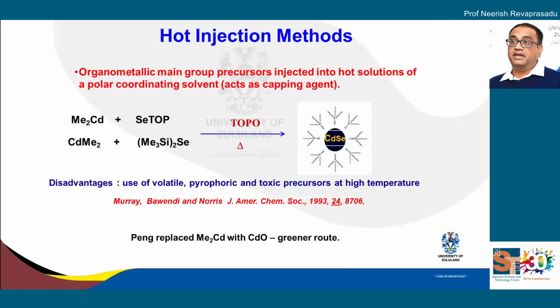Now, going back to the history, this was the first route to making cadmium selenide quantum dots, which won the Nobel Prize in 2023. They use dimethyl cadmium and trioctylphosphine selenide, or dimethyl cadmium with this bis(trimethylsilyl) selenium complex, and thermally decompose the two sources in trioctylphosphine oxide to give you what is known as TOPO-capped cadmium selenide. There are disadvantages, as I mentioned, because the starting material is dimethyl cadmium. There are videos on YouTube that show you how they make this material, but you have to be extra careful in making sure that this dimethyl cadmium is not exposed to air, because it could explode. They are very pyrophoric materials and also very toxic.